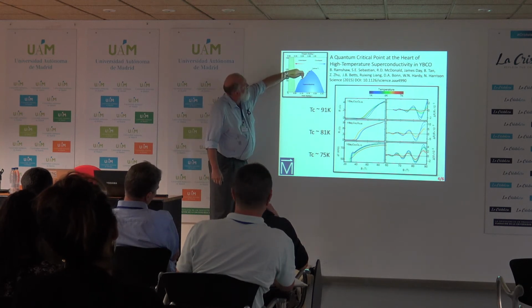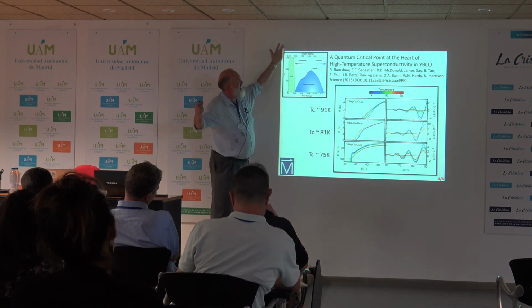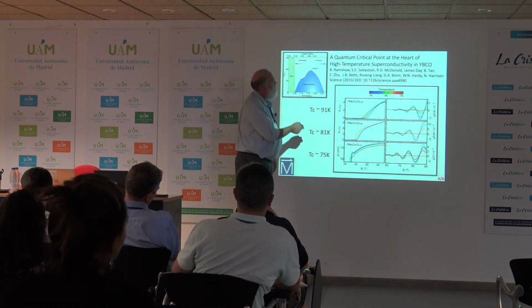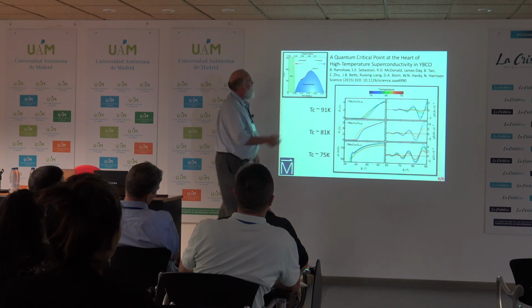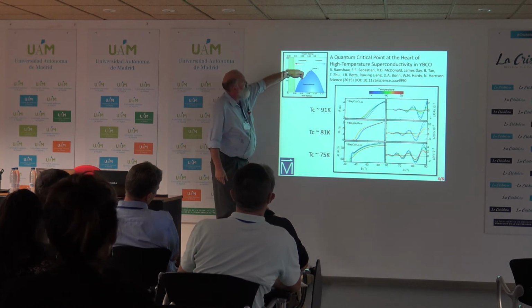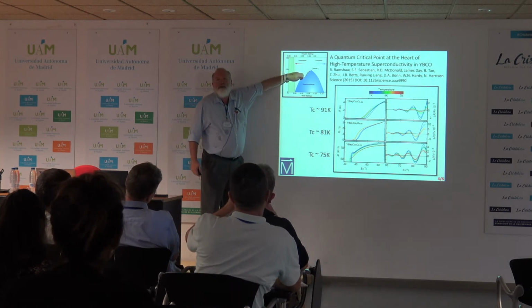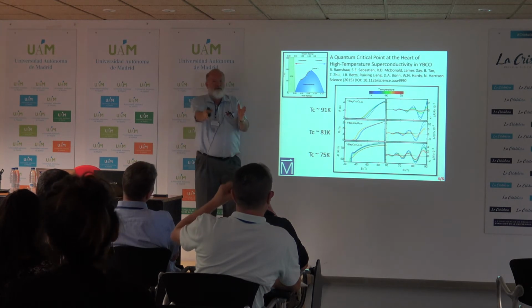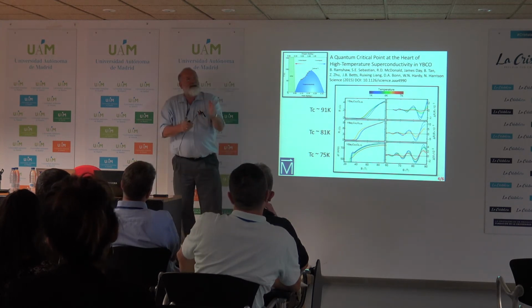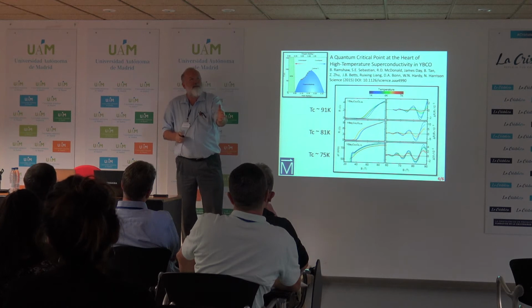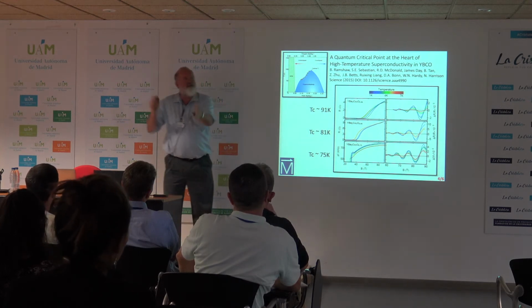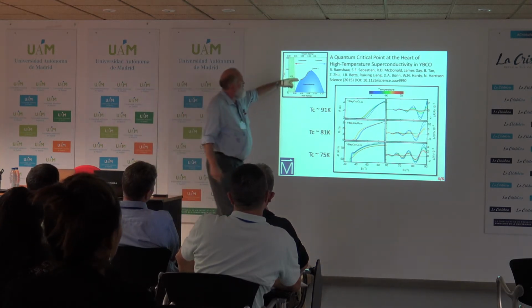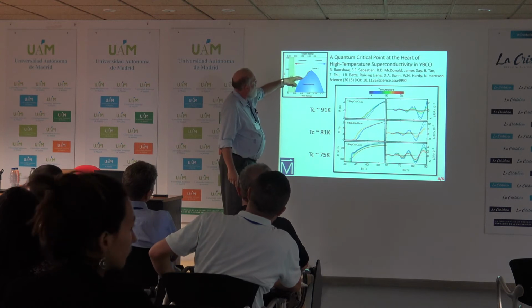And the reason is that you can make a highly ordered state. I can't make a highly ordered state. These geniuses from University of British Columbia can make a highly ordered state where the chains are half occupied with oxygen. Every other chain is empty, and the remaining chains are half occupied. So it's a very ordered state, and so they get very clean metallic behavior, and you see quantum oscillations.